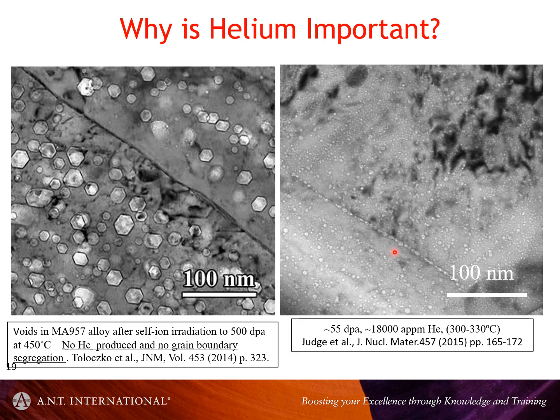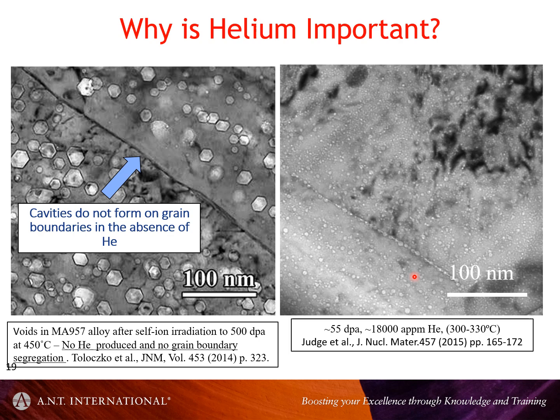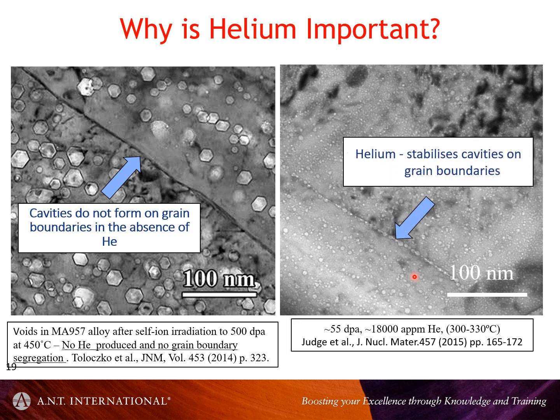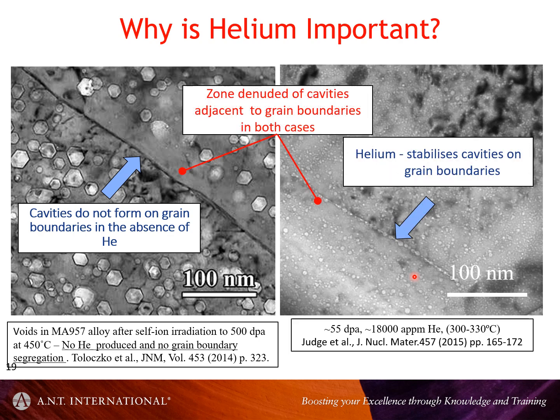It gets to the boundary, and there it stabilizes any vacancies, which can also make it to the boundary, and you end up with this higher density of cavities, or bubbles in this case, at low temperature. They're perforating the boundary when there's helium present. So cavities do not form on the grain boundary in the absence of helium, but helium does stabilize bubbles on the boundary.